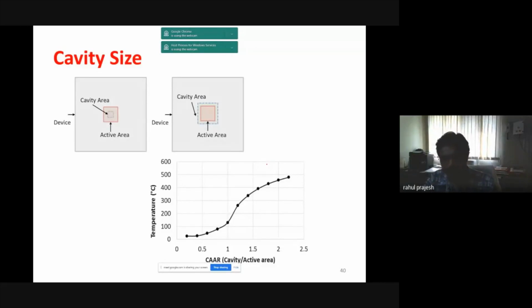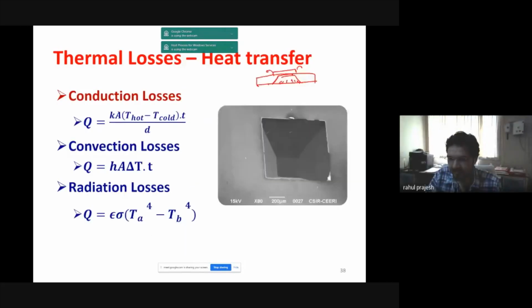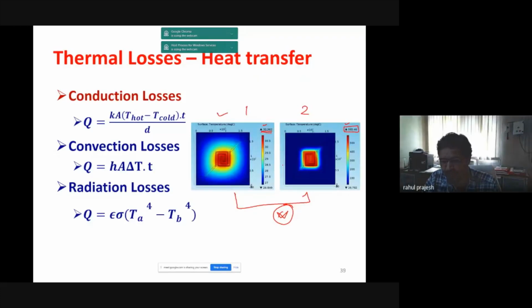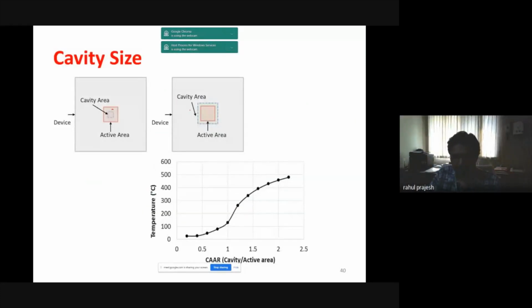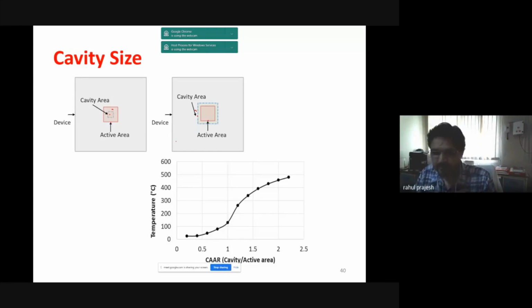Another important part of this is the cavity to active area ratio. Now you see this cavity. This is the cavity in the back side, and if you see, this is the kind of active area on the front side. Now what should be the ratio? If you see these two images, this is the cavity area and this is the active area. And here the active area is smaller and the cavity area is bigger. Here the active area is bigger, the cavity is small. Now you need to choose your cavity area such that you get the maximum temperature for a given power.